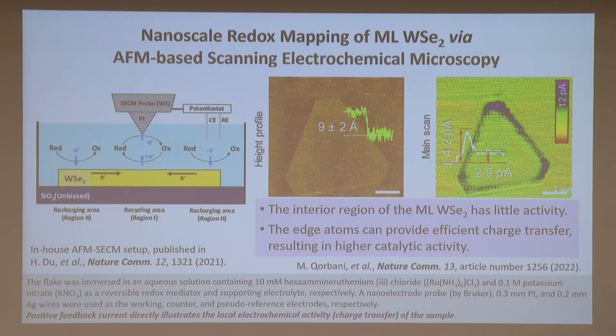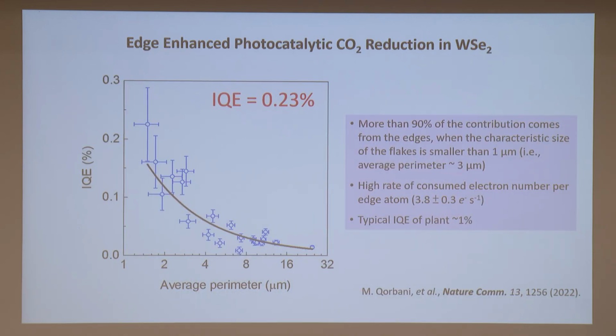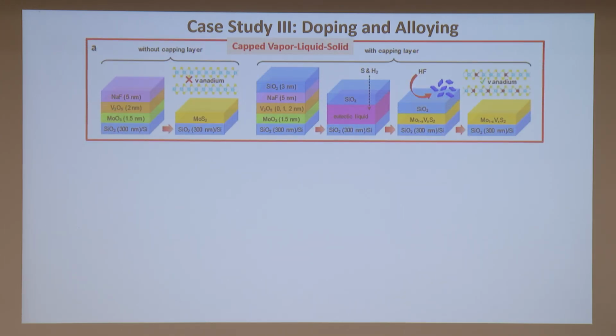So this type of activity is edge promoted, and we can even calculate it in terms of the size of the island. If it's too large, it's almost basal plane dominated and not really any enhancement. But as you decrease the size, you have more and more edge contribution. And at 1 micron, you can boost the activity by an order of magnitude and above. So this is a very quantitative analysis of how edges can contribute. Now, edges are useful. Basal plane with defect engineering is also useful. However, both of them could suffer from less stability.